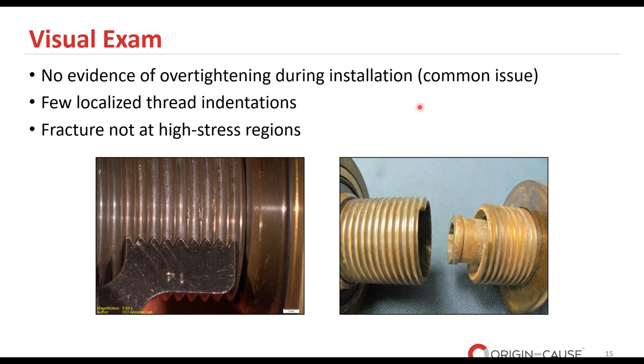So let's turn our attention to the visual exam of our brass faucet here. Some key findings really stood out. First and foremost, we looked at the installation process. Given that over-tightening during installation is a common issue, but interestingly enough, we found no evidence to suggest that this was the case here. This effectively eliminates one of the more frequent culprits behind failures like this.